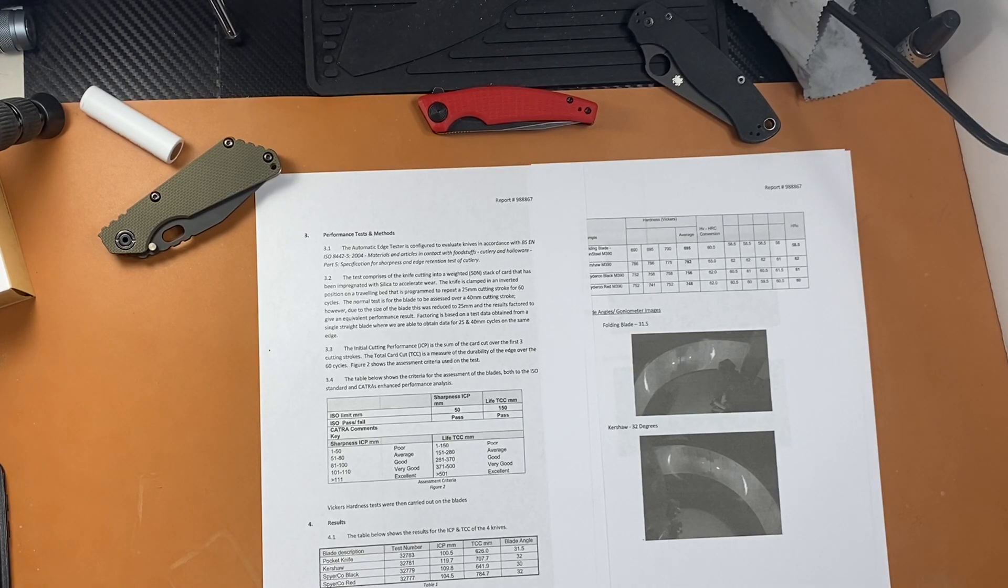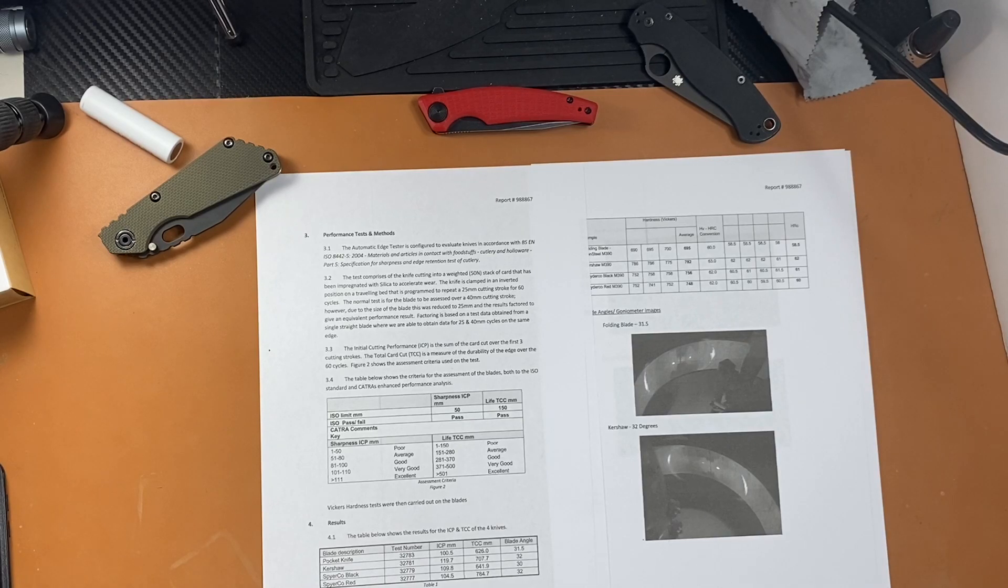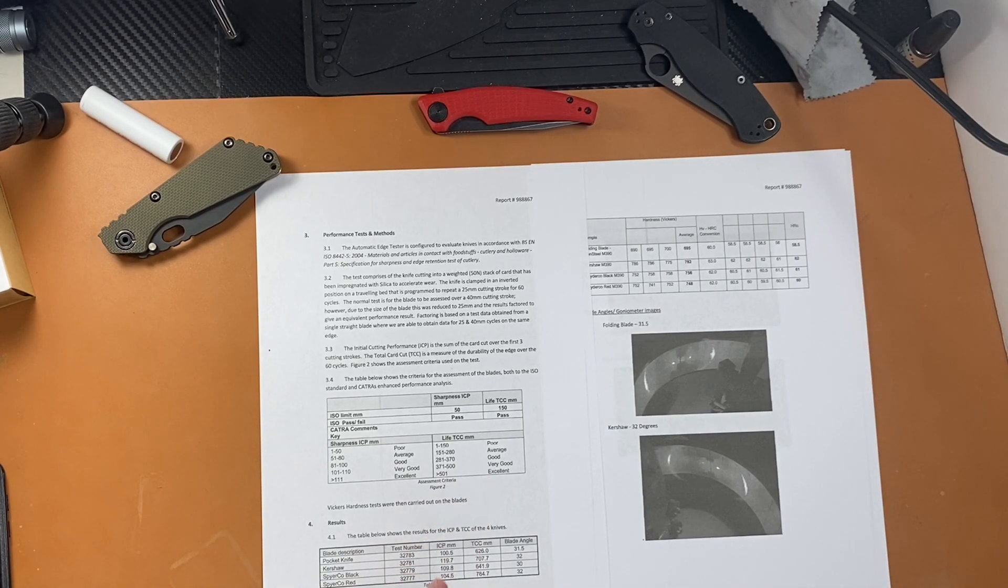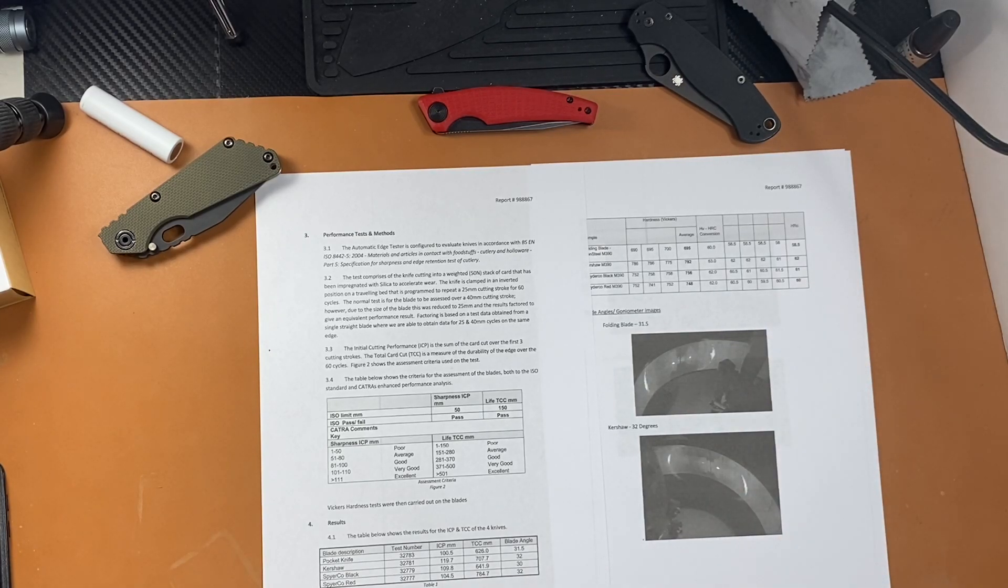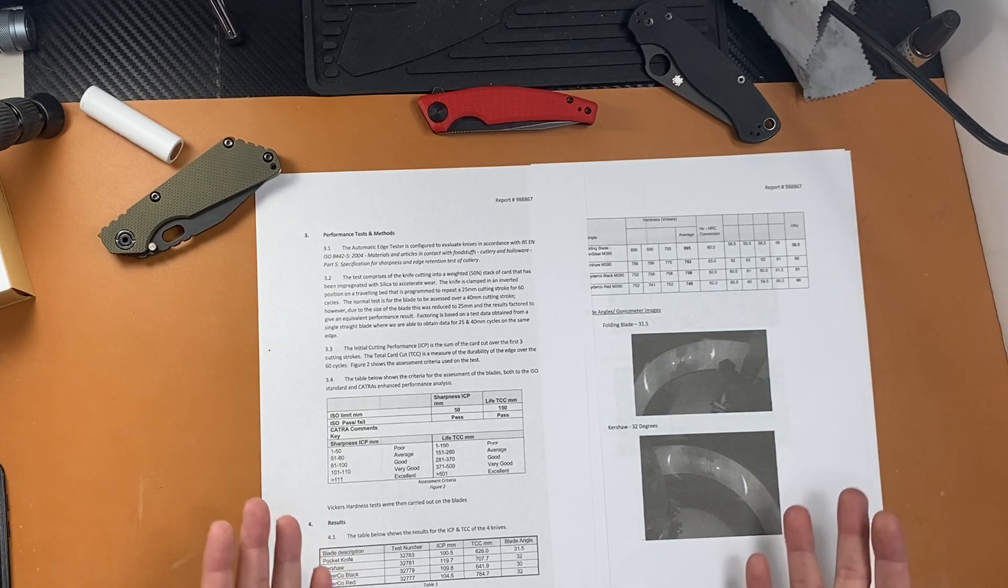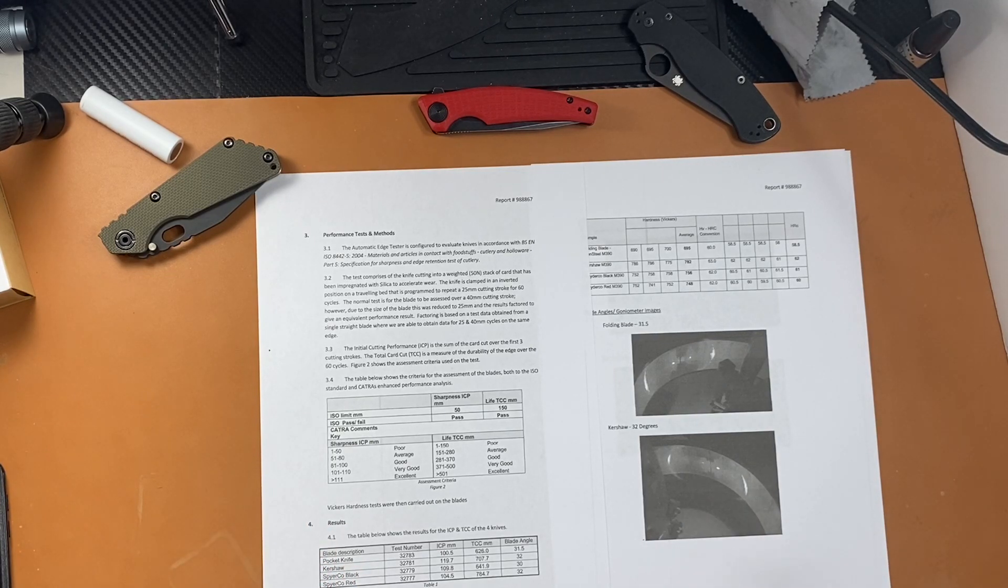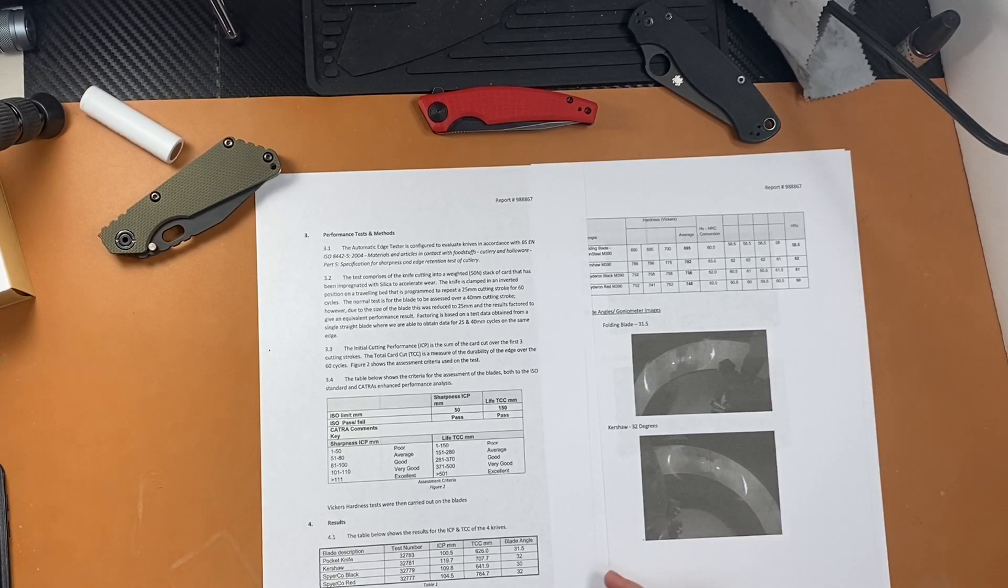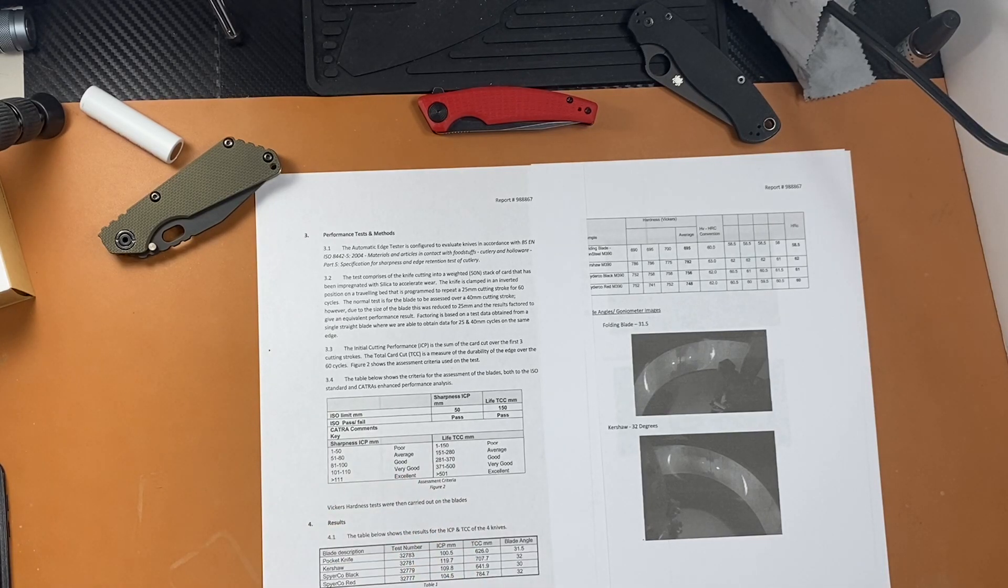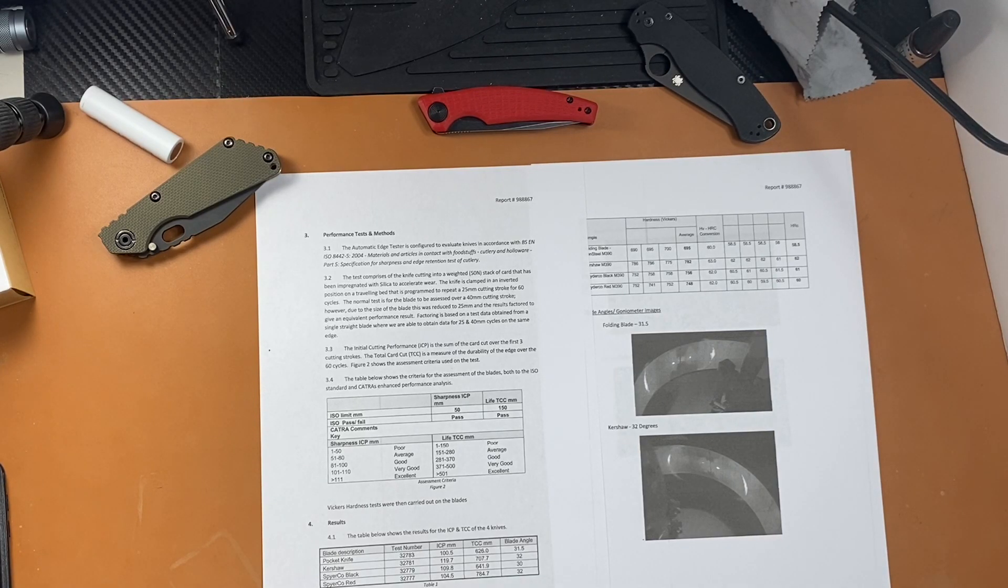That can be a lot of things. Not only is Kershaw obviously running their M390 hard, right? But are they heat treating it properly? Are they getting rid of the austenite? Are they doing those kind of things to make it cut good? And they must not be, because I mean, it's doing good, but it's not doing as good as the Para 2 at a lower HRC. So really interesting stuff. This was a community-funded project. We wanted to see a very scientific way. CATRA, this is incredibly. You've got a report, it's all put in a machine, so there's no human error. And you can see that higher HRC M390 versus lower HRC M390, you're going to have a lot better edge performance. I mean, a dramatic difference. Almost 160 more cuts.